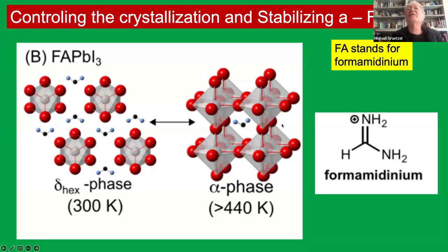So first of all, I mentioned this particular A-cation, which is called formamidinium. Formamidinium lead iodide is actually the preferred composition formulation for photovoltaics. It has the lowest band gap. So optoelectronic properties are superior to other A-cations like cesium or methylammonium. However, there's a big drawback, a big caveat. This phase is not stable below 100, say 60 degrees Celsius.